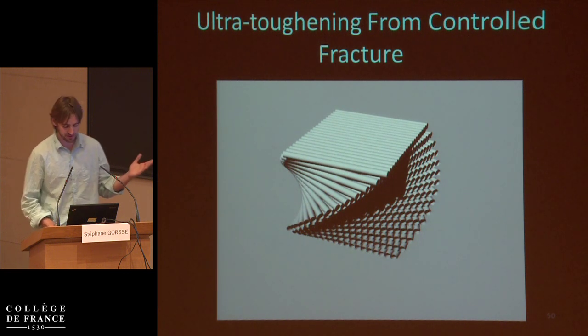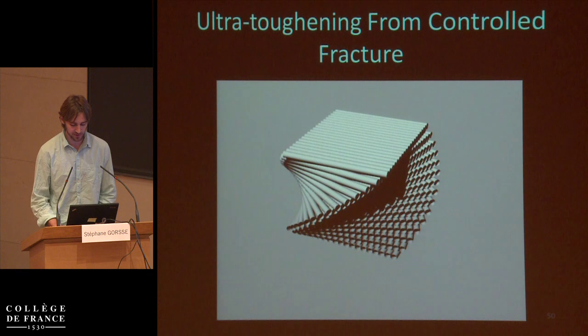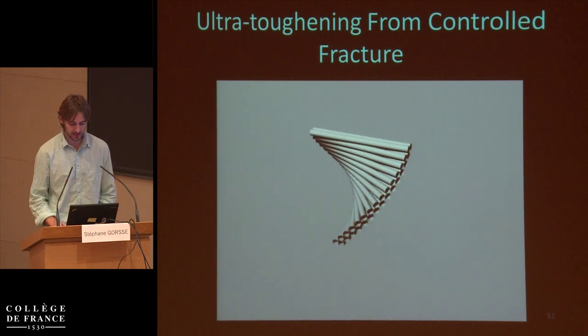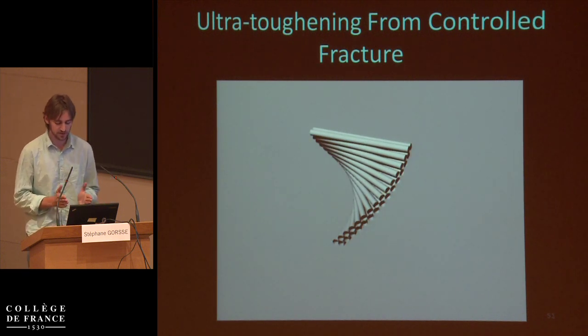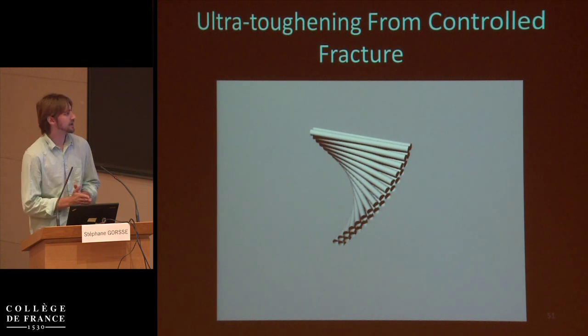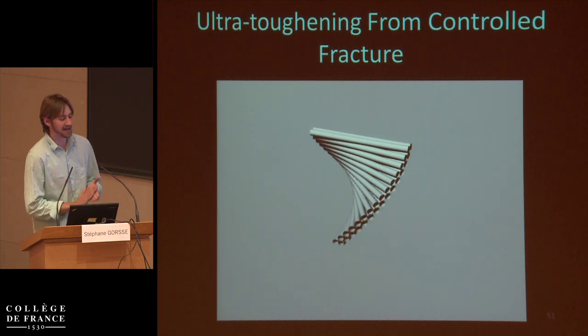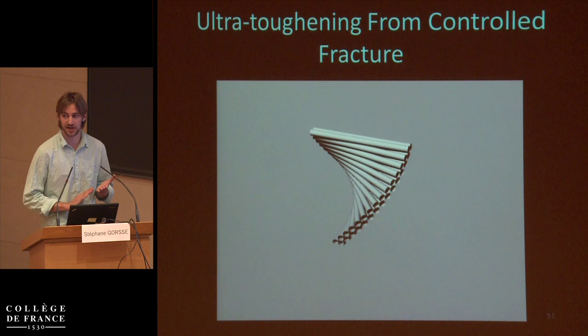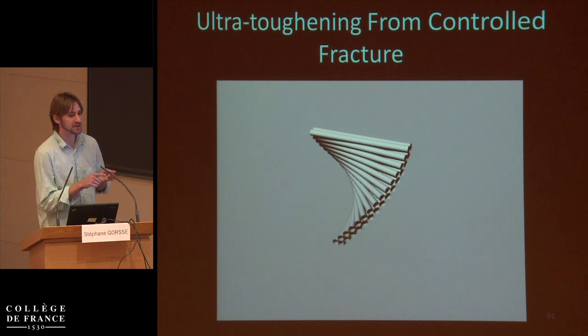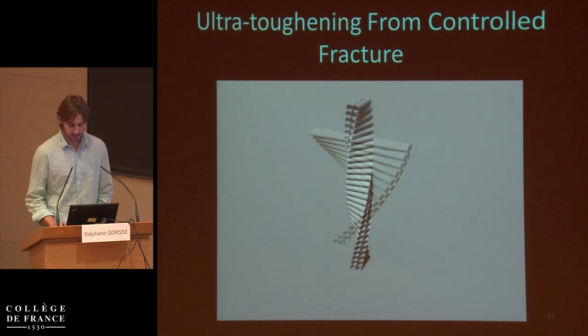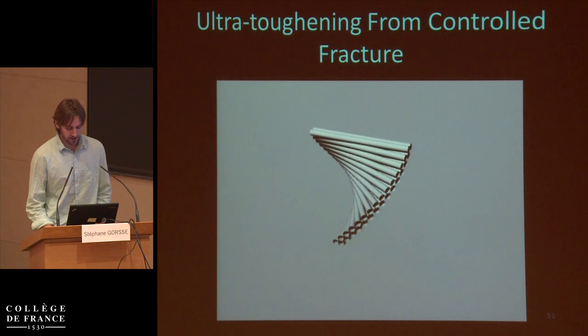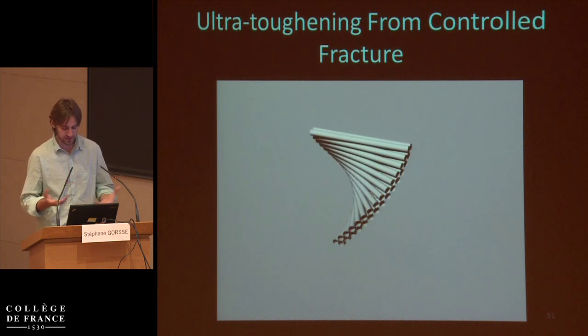So first we just start with a basic model of a helicoidal composite, and I reduce that model down to just two parallel fibers per layer. And what this represents is the path of a fracture. Just imagine a fracture traveling between these two fibers in each layer. Now, just that alone, you'd expect it to travel, and so it basically follows a helicoidal surface.